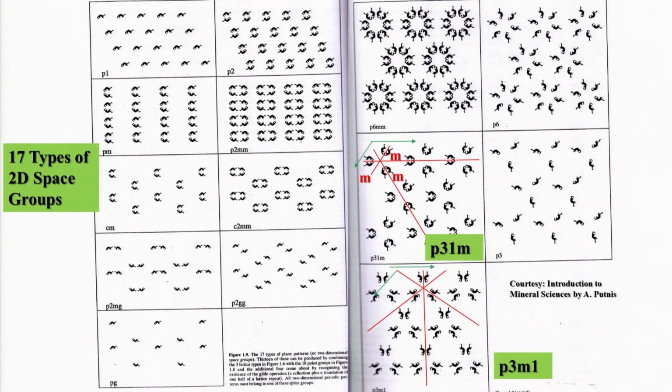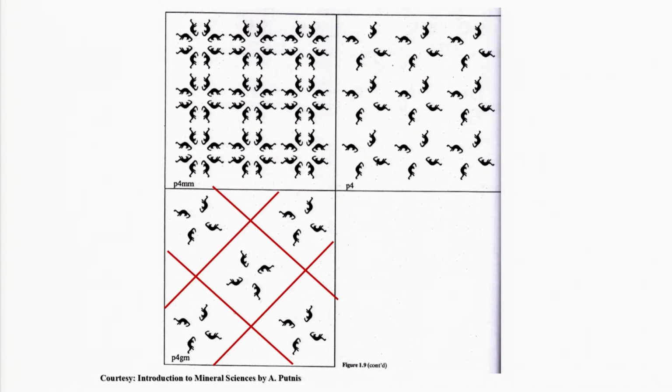We have the square lattices now. So, we have here the simple one here, P 4 mm. You can immediately find out this is the position of the vertical 4-fold axis, and this is one plane of symmetry here, another plane is of this orientation. You can also think of another set of mirror plane of this orientation and another set of mirror plane of this orientation. So, this mirror plane and this mirror plane are at an angle of 45 degree.